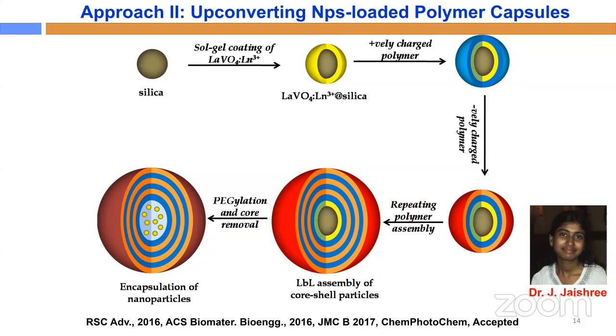She wants to synthesize upconverting nanoparticles, which typically needs a very high temperature, for example 500 degrees centigrade, as the reaction temperature to prepare the nanoparticle. So what she did, she started with the silica. The silica was coated with lanthanum vanadate doped with lanthanide ion, coated by the sol gel method. And then once this was done, with the core shell particle coated with lanthanum vanadate, she heated this at 500 degrees centigrade so that all the lanthanum vanadate will be very highly crystalline.